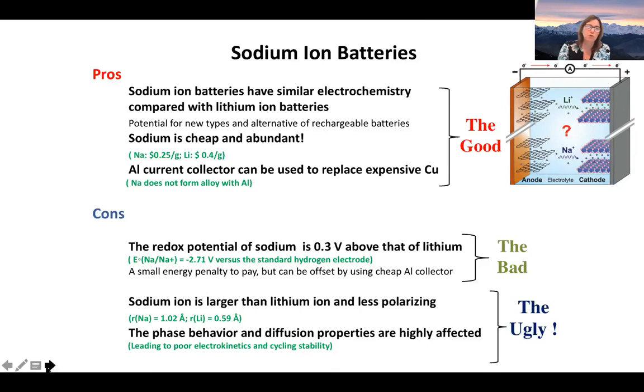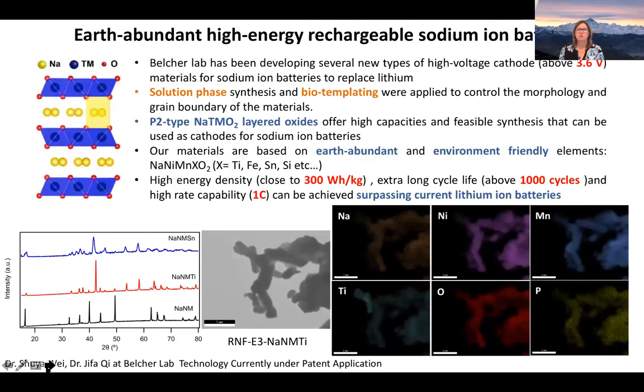And so my students using genetics, so I'm seeing this again, learned how to engineer around that and make these new combinations of materials that hadn't been able to be made at the nanoscale before. And what they did was actually make very high energy density materials that have very high cycle life. So some of the capacities surpass current lithium-ion batteries with cycle lives above 1,000.